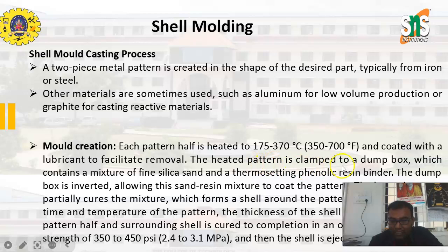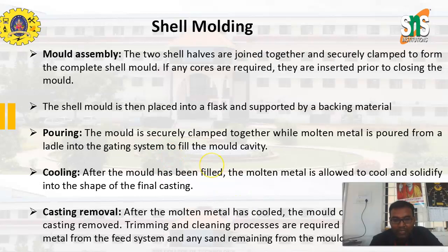The heated pattern is clamped to the dump box, which contains a mixture of fine silica sand and a thermosetting phenolic resin binder. The dump box is inverted, allowing the sand and resin mixture to coat the pattern. The heated pattern partially cures the mixture, which forms a shell around the pattern. Depending upon the time and the temperature of the pattern, the thickness of the shell is around 10 to 20 mm. Each pattern and the surrounding shell is cured to completion in an oven, giving it a tensile strength of about 350 to 450 psi, that means 2.4 megapascal to 3.1 megapascal, and then the shell is ejected from the pattern.